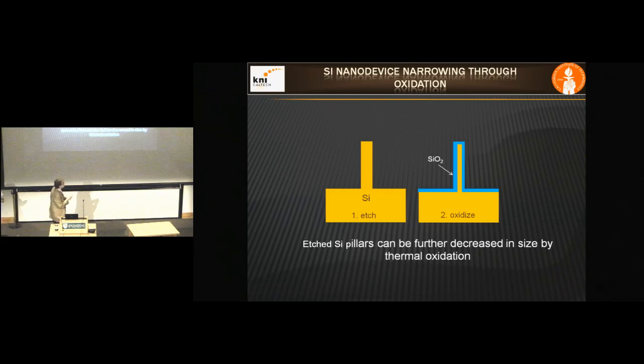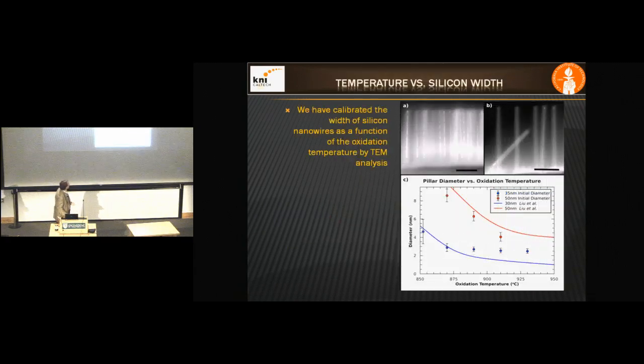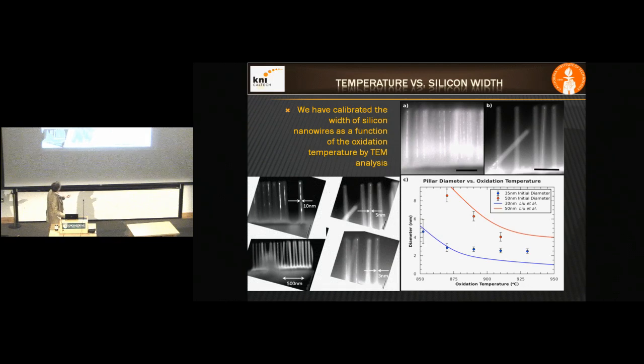And at some point, this oxidation process actually stops because there's no oxygen diffusion through this compressive silicon dioxide. And you can make structures that are very stable, that have silicon pillars within oxide encapsulants. Well, you can make them as small as you want to, really. Well, maybe you can't go much below 2 nanometers. Okay, in this case, this shows you the diameter of whatever pillar you get as a function of the temperature that you've oxidized at. You can leave this in the furnace for 5 hours or 10 hours. It's okay, because the diffusion stops. Okay? And you can make whatever size structure you want by dialing in the temperature. So at 3 nanometers, you would dial in, I don't know, some temperature over here. You basically end up having this capability of making smaller structures than you lithographically started with.